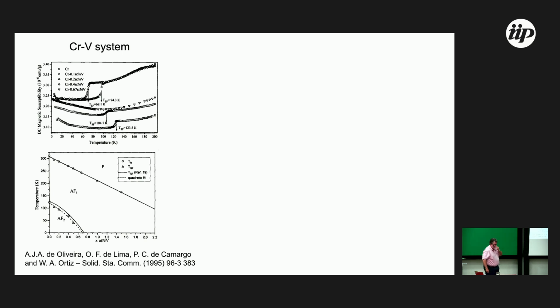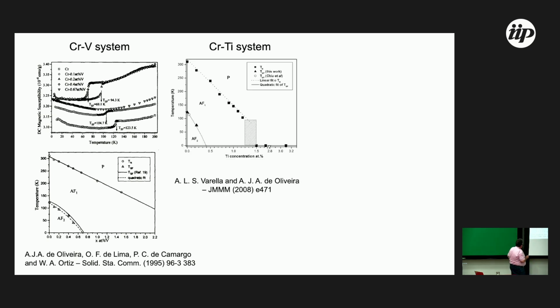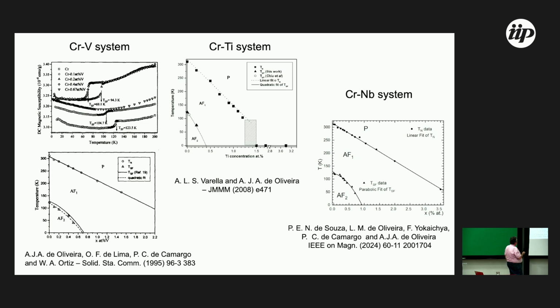Discuss about the chromium-vanadium system, my system studied many, many years. This magnetic phase diagram of chromium-vanadium, as expected, shows a linear decrease of Néel temperature, because vanadium is on the left side of chromium in the table, one electron less. 1% of vanadium in chromium, a decrease of 100 K of the Néel transition. 311 to 210, okay? And this magnetic phase, the AF2 phase, decreases with increasing concentration, but disappears around 0.7%.